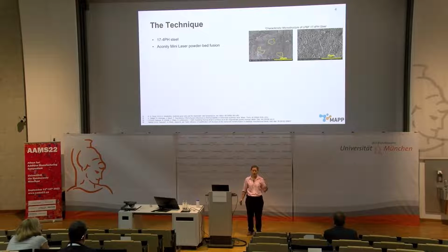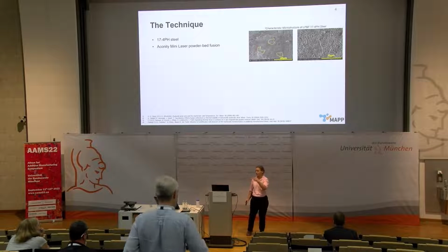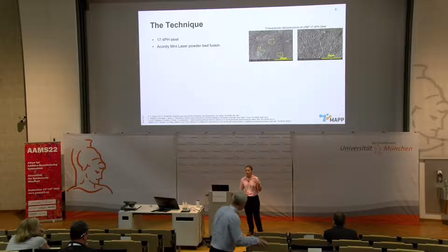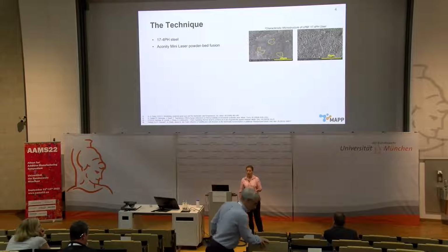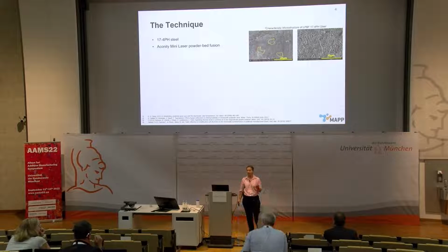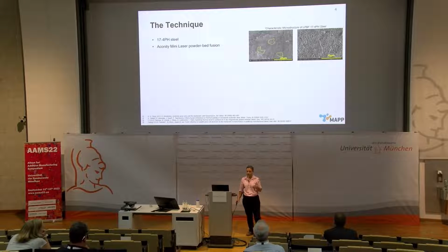we get the characteristic microstructure that you can see there on the right hand side. So we've got fairly large grains of the sort of 10 to up to 100 microns in size. And inside those grains, we see the classic solidification cells that we've heard discussed, again, particularly in Matteo's talk, talking about those solidification cells. And they're very fine, often around a micron in diameter, sometimes smaller, sometimes a bit bigger, all depending on the